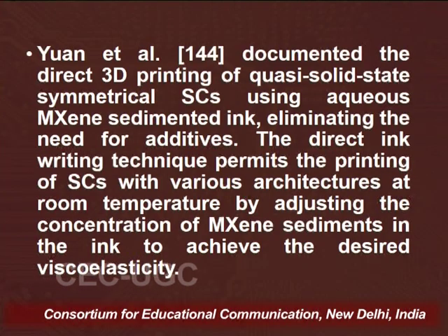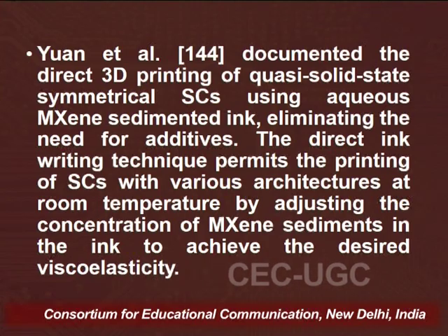So, whenever we develop wearable energy devices, we keep these parameters in mind. In one of the papers, they demonstrated the direct 3D printing of a quasi-solid state symmetrical supercapacitor, using aqueous MXene sediment ink and eliminating the need for additives. So, the direct ink writing technique permits the printing of supercapacitors with various architectures at room temperature by adjusting the concentration of MXene.